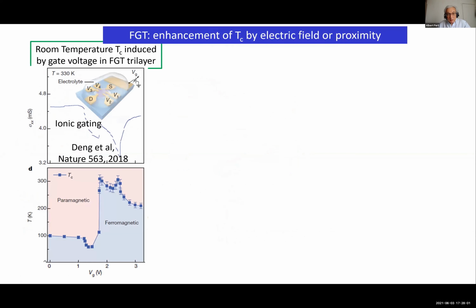So now I come back to the problem of the enhancement of the ordering temperature, for example, the Curie temperature of ferromagnetic 2D magnets by electric field or proximity. An electric field, because a small gate voltage can induce a very large electric field, can be used to manipulate the electronic property and the magnetic property. For example, by applying a gate voltage by ionic gating, it is possible, as a function of the voltage you apply, to go from this temperature to this temperature, a little above room temperature. So this is one other way to manipulate the Curie temperature of this FGT.